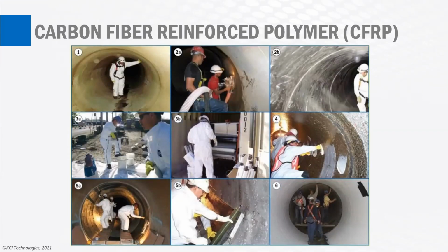This slide kind of just walks you through the different stages. So, the main stages: you obviously go into the system, your PCCP line, and you look at the existing condition. Is there a lot of spalling concrete coming off the inside walls? Do you need to individually address those prior to putting on your layers of carbon fiber composite? A very important part of an effective CFRP system is the surface prep, where you have to hydroblast the inside surface of the PCCP. And if needed, you may need to make additional fixes to concrete portions that may have fallen off, that may need to be reinforced and fixed and patched prior to application of the carbon fiber.